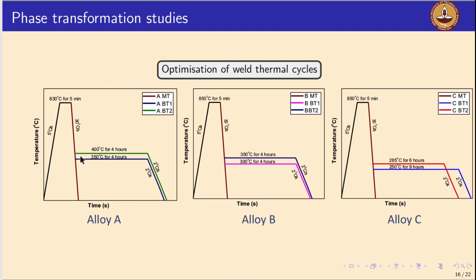For alloy A, we can identify suitable isothermal bainitic holding temperatures, and we can vary the temperatures and identify the transformation kinetics using the dilatometry analysis. The important condition to generate a carbide-free bainitic microstructure is that the final microstructure should not contain any martensite. If martensite is present, the structure becomes brittle and susceptible to hydrogen-induced cold cracking. We should also understand that the holding temperatures should always be above the MS temperature. Therefore, we carry out extensive dilatometry analysis, first understanding the martensite start temperature, MS, and what would be the ideal isothermal bainitic holding temperatures.